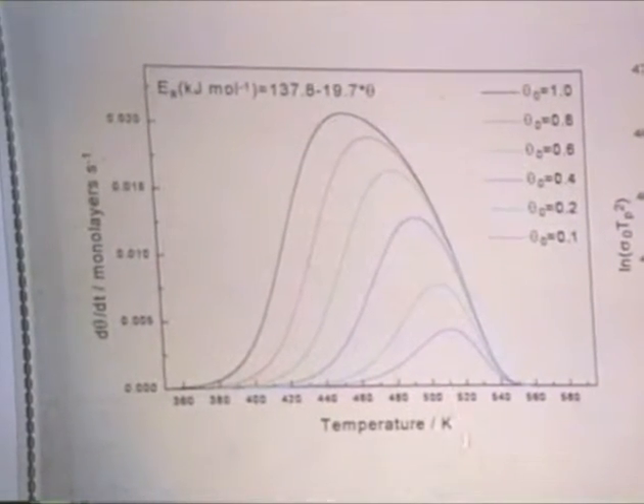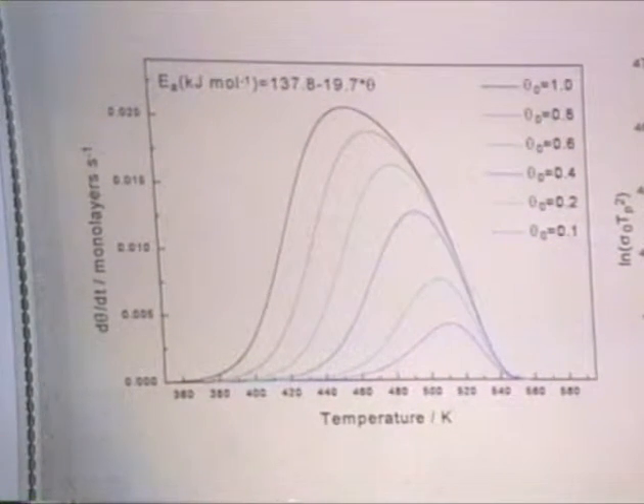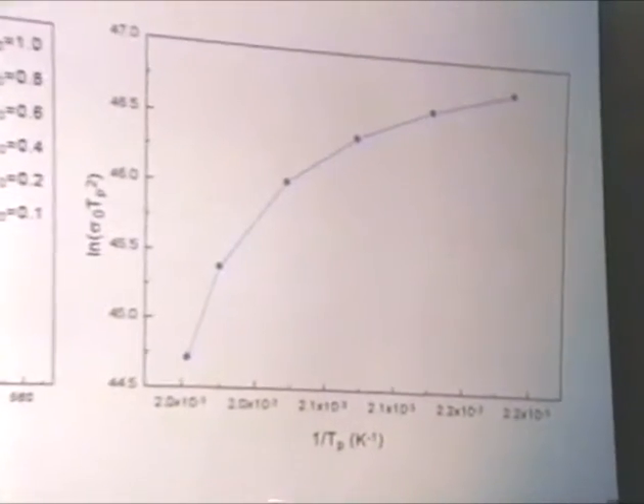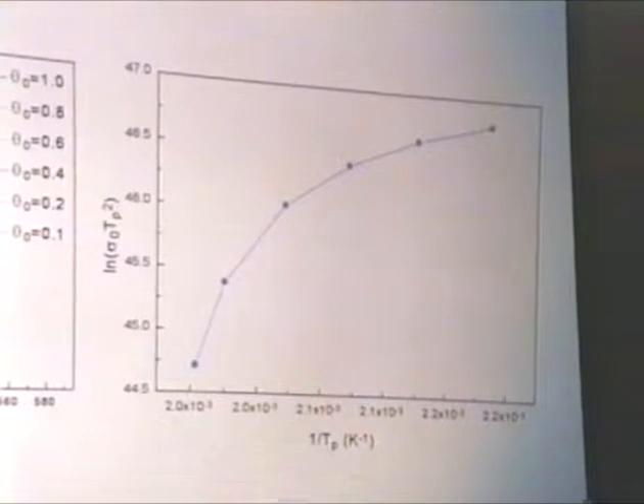These are the results. Of course, I was able to pick an equation that would allow a peak temperature shift across the entire experimental data range that we saw for the 300 Kelvin adsorption. You'll notice that the peaks are not the typical asymmetric first-order desorption shape, so the peak shape has been altered. And when you do a corresponding second-order Redhead analysis on this data, you don't get a linear fit. And so this indicates that if we have a coverage-dependent activation energy case for the desorption of room temperature CO, we would not get apparent second-order kinetics. So we don't believe this is an explanation for what we have observed.